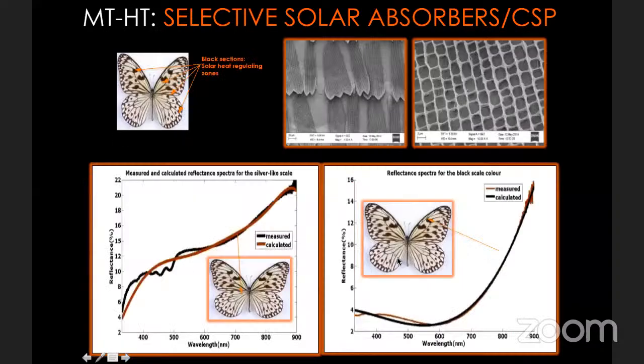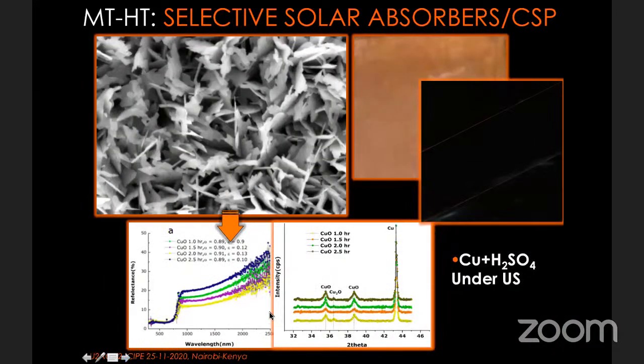So the same thing here for this butterfly that many of you have seen. The black spots here have a selectivity like a solar absorber, as you remember. Nearly zero, a minimum of reflection in the visible and near infrared, and a high reflectance in the near infrared and infrared. The white section doesn't have that kind of behavior. So you see clearly the black section is used to heat the body of the butterfly, any butterfly having black stuff. And so the idea is to create surfaces which would behave like that.